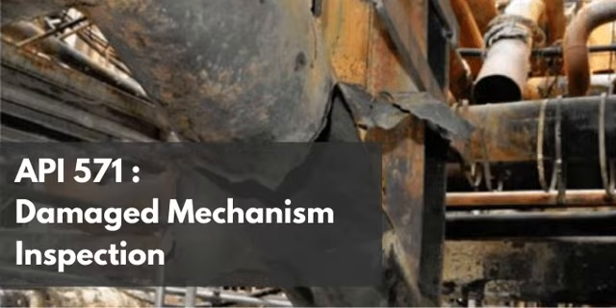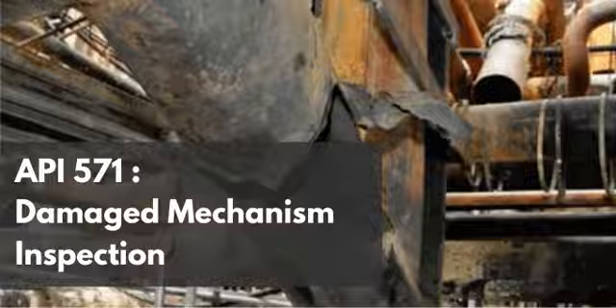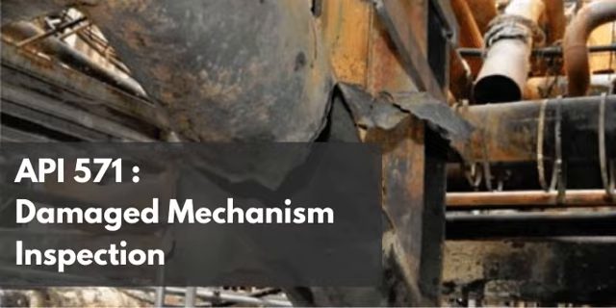It's like pre-soaking our flexible sponge in a liquid armor that hardens into a force field, so that later on, it is physically impossible for the dirty water to ever soak in. A very apt analogy. By heavily engineering the surface chemistry ahead of time to intentionally form that specific, ultra-stable aluminum oxide, you protect the highly susceptible iron and chromium-rich matrix underneath from ever even seeing the high-carbon environment. It is brilliant engineering.